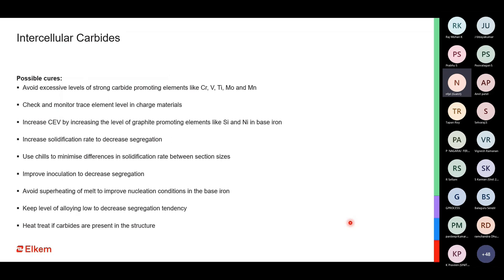How do you solve it? What can be the possible cure for carbides? The possible cure, the most primary one, is to ensure that we have control over the carbide promoting elements. One of the most common ones in case of gray iron is chromium, which we do add sometimes to achieve the mechanical properties, but excessive chromium is always disadvantageous for the castings. We have to make sure that we have control on these trace elements. We also have to control the rate of solidification. Fast solidification means less time for the carbon to come out as graphite. And when there is less time for carbon to come out as graphite, it will combine with iron to form iron carbides, and that is the phase which we do not want in our castings.